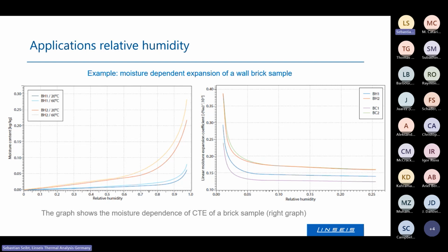On the left side, you see the moisture content versus relative humidity. So the brick sample was exposed to relative humidity levels at different temperatures, 20 degrees and 60 degrees, across two batches.